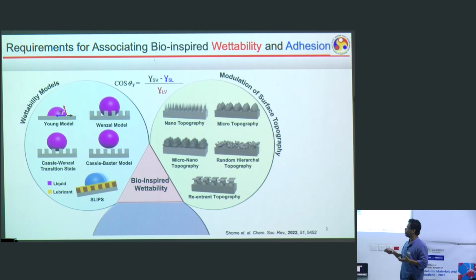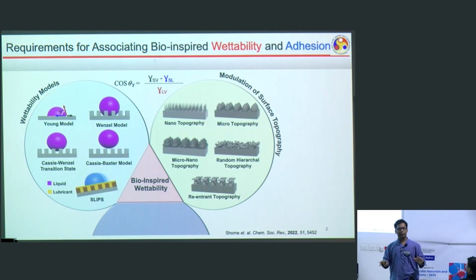Okay, balancing of the forces acting on this droplet, if you have a 2D projection, on the right-hand side and the left-hand side, two unique points. So basically, this red one is the surface tension, right? This is gamma LV and its cosine component, plus this gamma SL equals gamma SV, right? It's just the balancing of the force. It's not a magic formula.